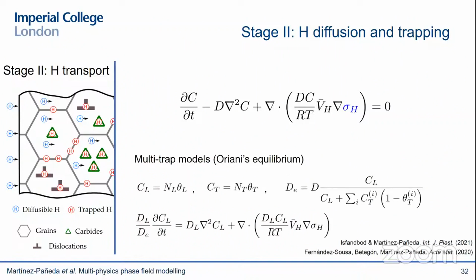Another important aspect of it is that hydrogen not only travels freely through the crystal lattice, it's also trapped at microstructural features like grain boundaries, carbides, or dislocations. So those microstructural defects will sequester the hydrogen away from the crystal lattice. So we have developed more sophisticated models based on Oriani or McNabb-Foster, where we can account for this distribution of hydrogen within the microstructure. We can predict where exactly the hydrogen lies.